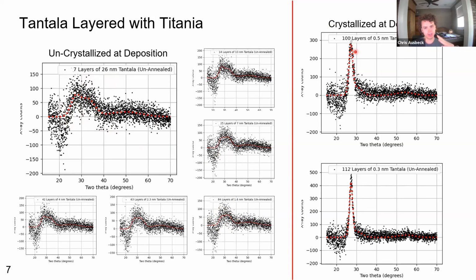However, for 100 layers of 0.5 nanometer tantala and 112 layers of 0.3 nanometer tantala, we see something very different. We had yet to bake these, but they still have crystallized. And you can see these peaks here.